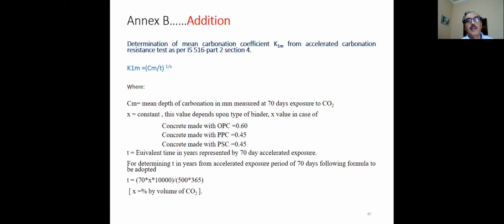And we have also put an annexure with this, which gives the determination of mean carbonation coefficient from accelerated carbonation resistance as per 516. Now these equations which have been drawn are all based on accelerated carbonation testing which we do in the laboratory at 1% level, 3% level, 4% level. We have gone up to the 4% level.